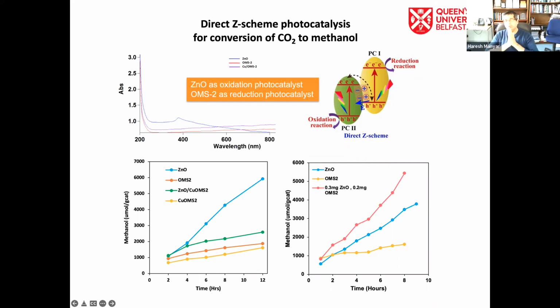In this case, we combine these two metal oxides. Zinc oxide absorbs light in the UV region, around 370, 376 nanometers, depending on the synthesis of the material. Metal oxides like copper oxide or manganese oxide absorb strongly in the visible region. For example, the absorption will be much higher in the region of orange light or red light. So we combine these two metal oxides mechanochemically, grinding them to achieve very high molecular-level mixing between the two photocatalysts. Then we use them and compare the performance.